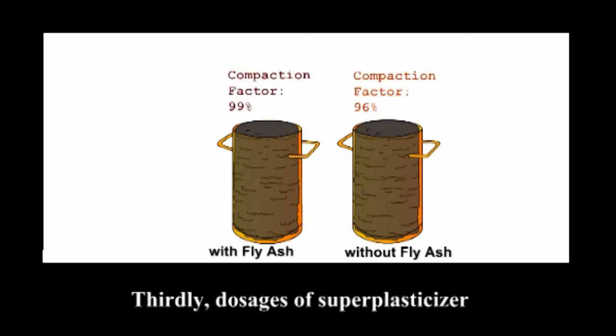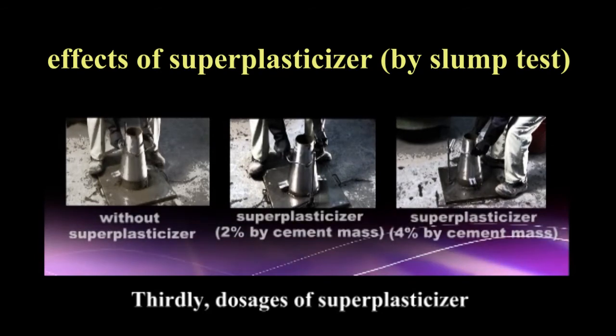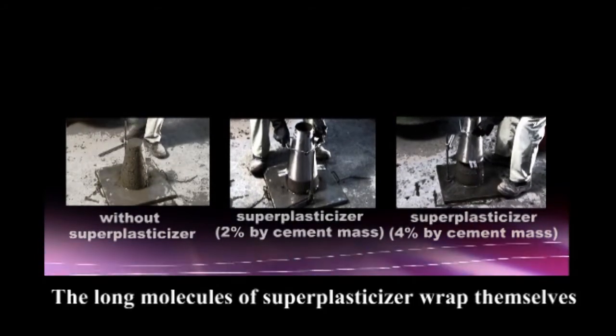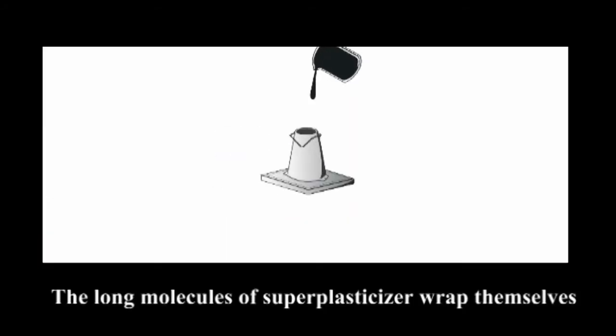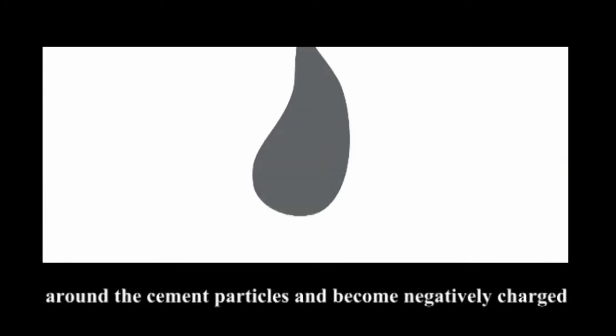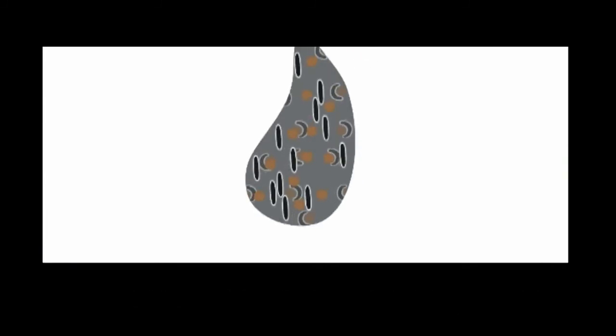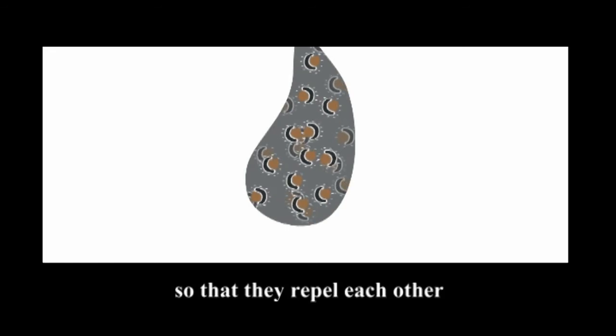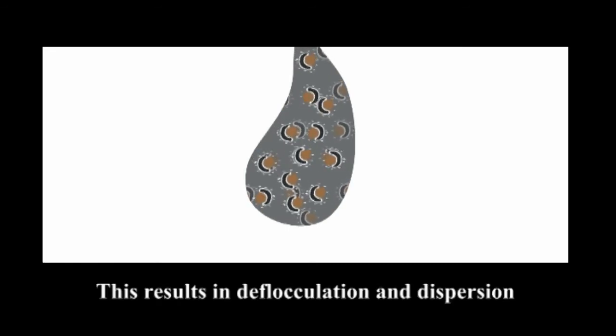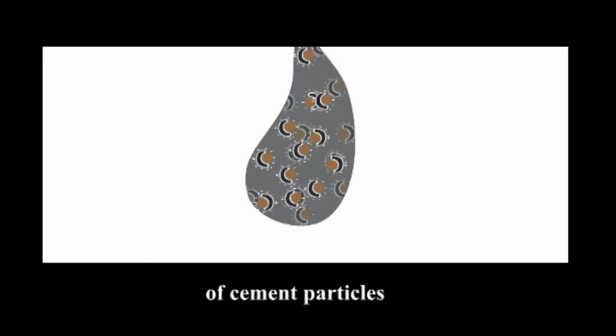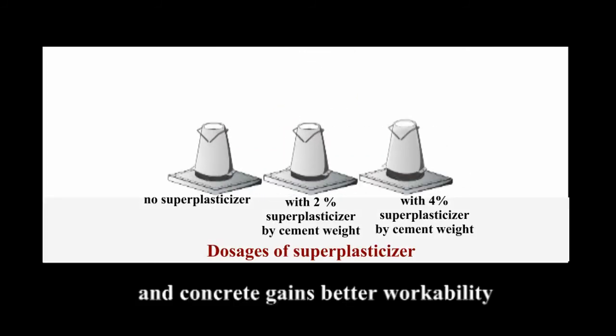Thirdly, dosages of superplasticizer. The long molecules of superplasticizer wrap themselves around the cement particles and become negatively charged so that they repel each other. This results in deflocculation and dispersion of cement particles, and concrete gains better workability.